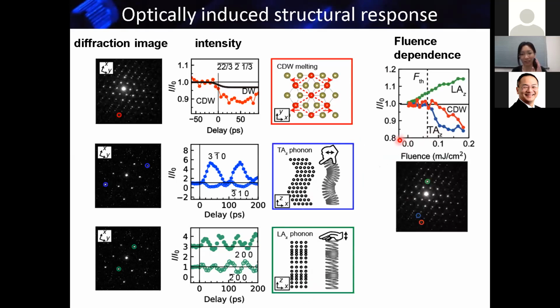We also measured its dependence on the pump fluence, and we see that when you excite the sample stronger and stronger, there's a threshold behavior in the CDW and also in the transverse acoustic phonon. So we can say that this transverse acoustic phonon is triggered by the CDW, but the longitudinal acoustic phonon is not affected by the CDW, which means it's generated by the usual photothermal mechanism. So this TA phonon is very unusual in this case.